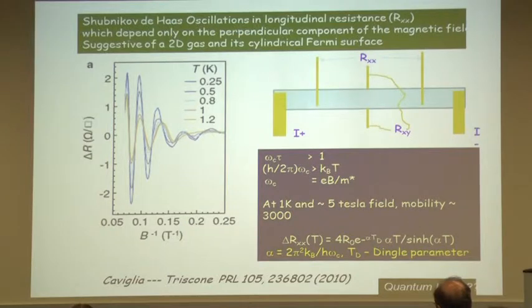And one can, by doing a measurement of magnetoresistance, figure out whether it is indeed a two-dimensional electron gas or not. So one has to do something called the Shubnikov-de Haas measurement. And so in the magnetoresistance Rxx, if you apply a perpendicular magnetic field, you see these oscillations in the resistance as a function of 1 over B. And if you tilt the field away from perpendicular configuration, the oscillations disappear. So that's a clear signature that you are dealing with a two-dimensional electron gas with a cylindrical Fermi surface.